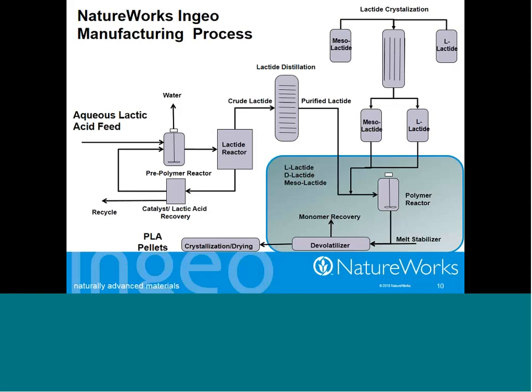Moving on then to the polymer process, we've got our set mixture now of L, D and mesolactide that we're going to feed to the polymer process. This is a melt process, and it is a reversible equilibrium-based process as well. So, as I mentioned earlier, we control the molecular weight by the number of chain initiators that we add at the beginning of the polymerization process. Depending on the temperature of the polymer reactors, that sets the ultimate extent of conversion.